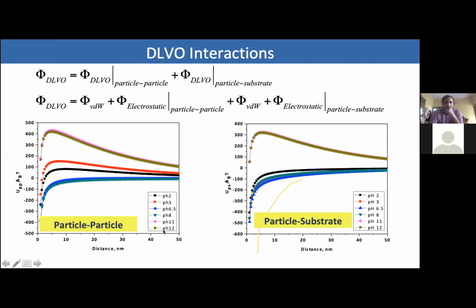However, if you take pH 12 and pH 11, or for that matter pH 2, you will see that the overall interaction potential in a certain distance range is positive. That means overall the interactions are repulsive. And a similar case also for the particle-substrate interaction as well. So the point that I want to make is that it is possible to tune both the particle-particle and the particle-substrate interactions by choosing a combination of particle, substrate, and the pH. And as I'll show, this will have some important consequences on the deposit formation.